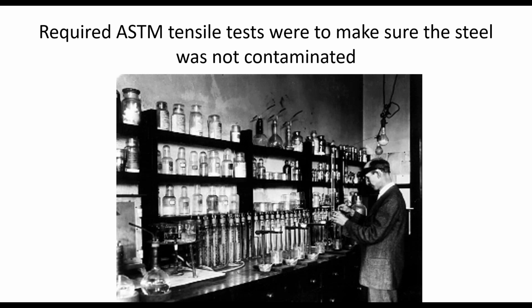If you order using ASTM material requirements for steel, then we're required to do a tensile test with every heat that we make. And for some reason, we've evolved to where people believe that I'm doing that tensile test to guarantee to you that you have those tensile properties everywhere in the casting. And that's fundamentally a misconception.